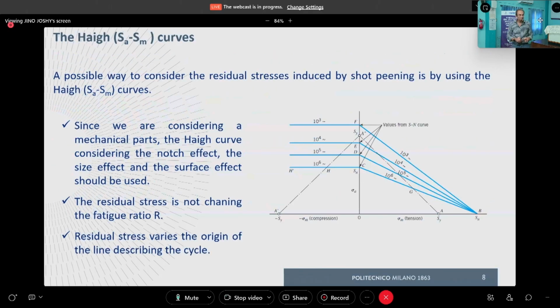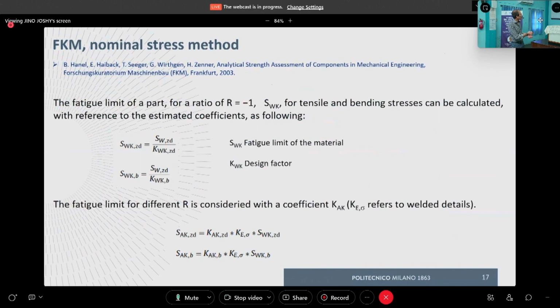Okay, let's go now to the possible way to consider shot peening in traditional fatigue design methods, that is to say, in methods that consider the Haigh diagram. We have already commented on this figure, and we said that here in the abscissa we have the mean stress of the fatigue cycle. Here in the ordinate, or vertical axis, we have the amplitude of the fatigue cycle, and the different blue lines correspond to the Haigh diagram, the fatigue limit for different numbers of cycles. So we can forget about 10^5, 10^4, and 10^3, and we can concentrate on the 10^6 diagram. And indeed, the triangle,